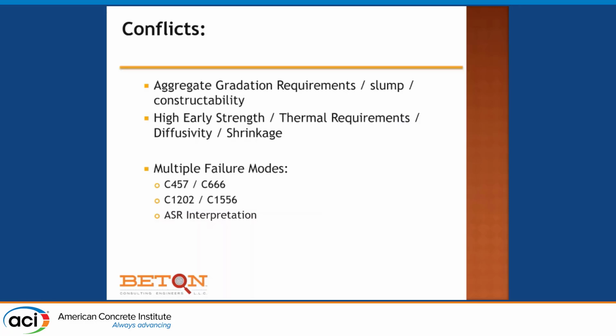We also have high early strength. I forgot to mention the transfer girders. They're 8 feet by 8 feet by 75 feet long, so they're also mass pours. So and 4,000 psi at 18 hours. So it's no problem. There's thermal requirements. We have to worry about diffusion coefficient. We have to worry about shrinkage, and we worry about cracking quite a bit. So we have our own acceptance criteria. We measure the resistivity of the concrete at about 2 hours, the surface resistivity.